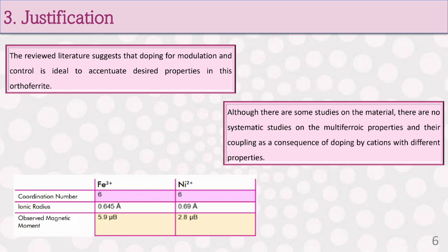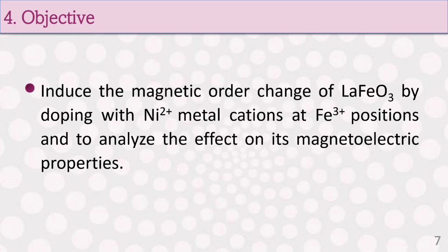The reviewed literature suggests that doping for modulation and control is ideal to accentuate desired properties in this orthoferrite. Although there are some studies on the material, there are no systematic studies on the multiferroic properties and their coupling as a consequence of doping by cations with different properties. Nickel is chosen because it complies with the Hume-Rothery rules as it has a difference between ionic radii of less than 10% and they have very similar characteristics as shown in the table, which gives the indication that it would be easy to substitute. The goal of this research work is to induce the magnetic order change of LaFeO3 by doping with Ni2+ metal cations at Fe3+ positions and to analyze the effect on its magnetoelectric properties.